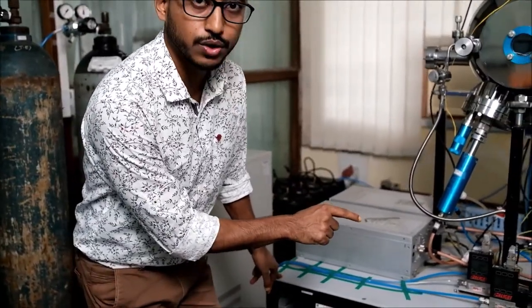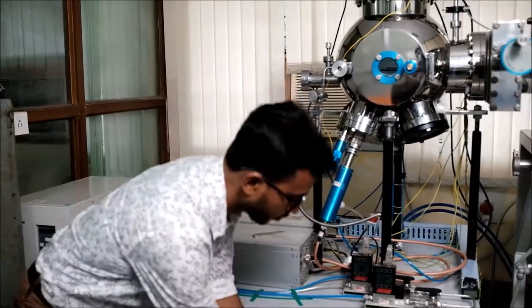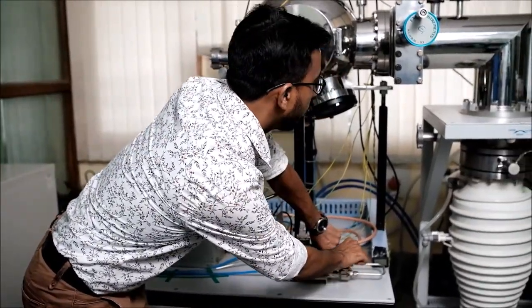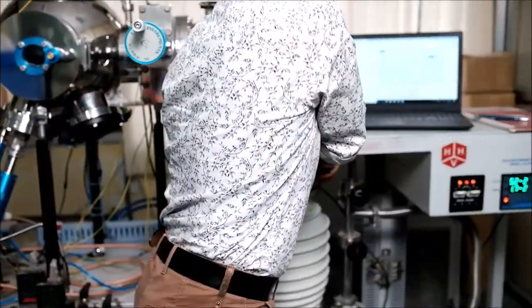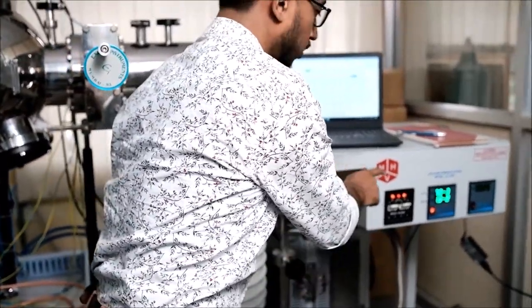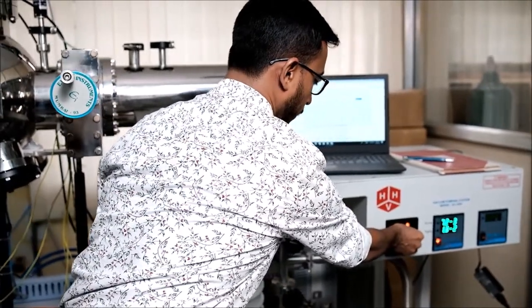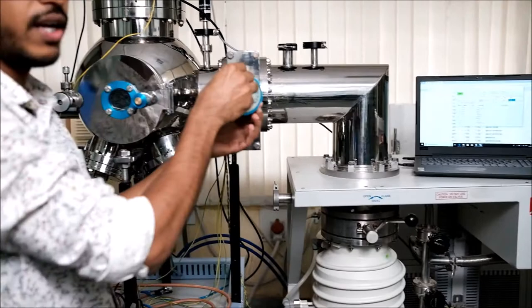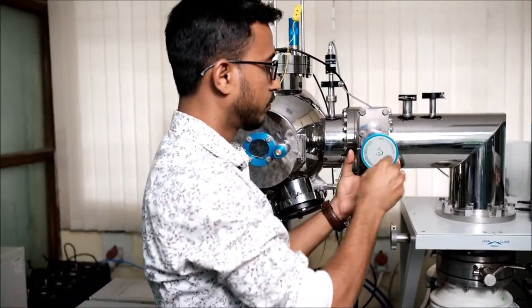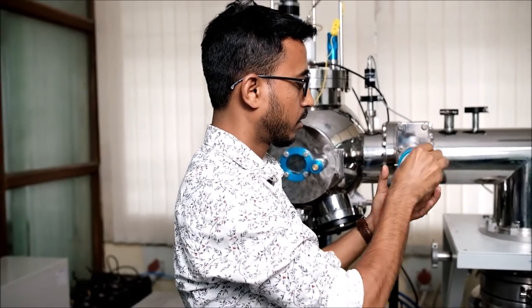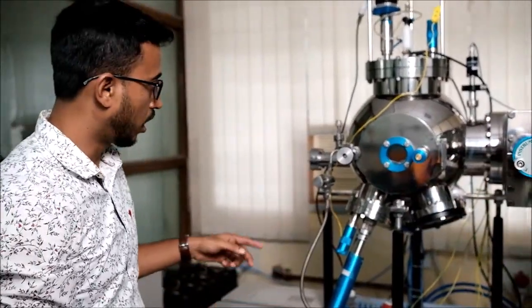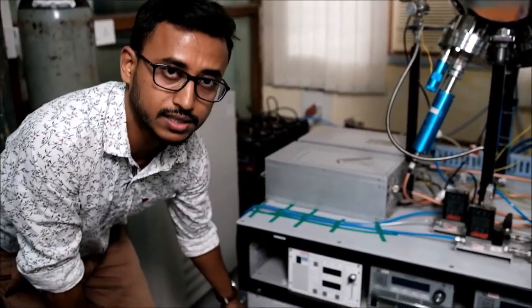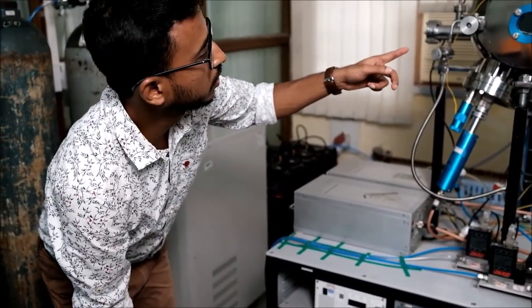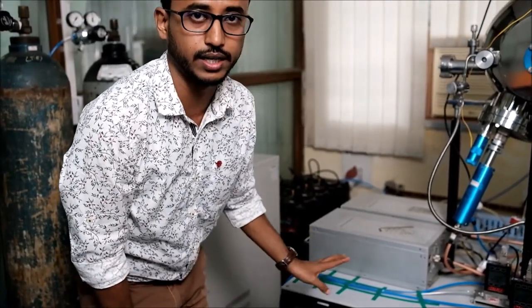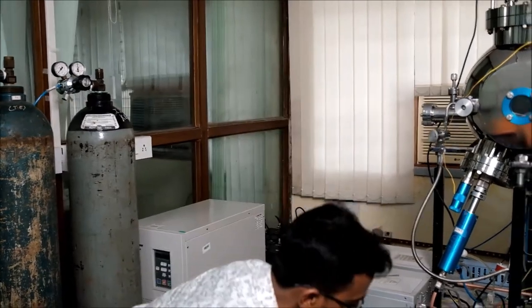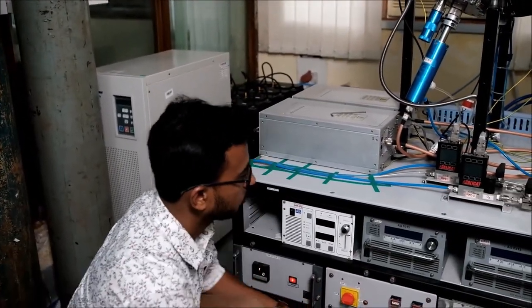Now I am ready to close the gas flow. So I will first close these two valves, and then the high vacuum valve will close, and now I can turn off the diffusion pump. And also this gate valve, I will keep it open. But now our substrate is at 153 degrees Celsius. I can only open the substrate once it reaches below 100 degrees Celsius. So I'll wait a few more minutes. I'll also close the power of two MFCs.